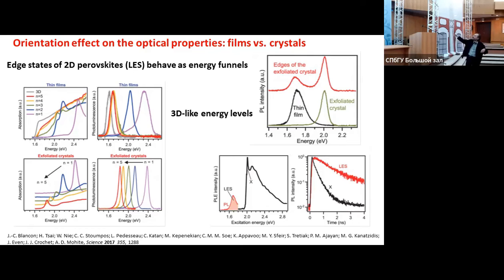And if you get a crystal that is damaged, or a bad crystal, or the edge of the crystal, you see both emissions. Both the emission that corresponds to the free exciton and the emission that corresponds to this trap-like state. And these trap-like states have much longer lifetimes compared to the free exciton, as expected.